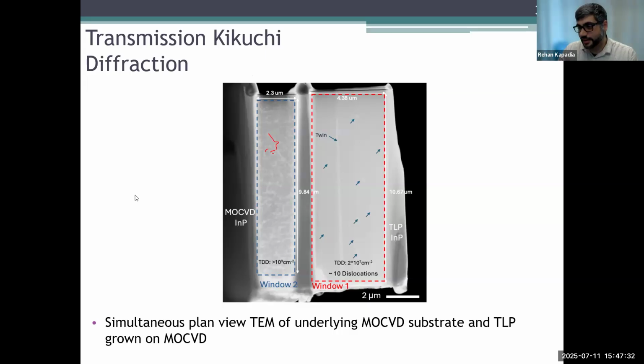And this is a very compelling proof, because essentially what we're doing is we're showing as much of the mesa as we can. So, we grew like a 10 by 10 mesa, and this is showing, or maybe I think this was maybe a 20 by 20 mesa. And then we're showing about 5 microns by 10 microns of it, which is limited just by the fact that it's extremely hard to do these kind of plan view TEM cuts and then imaging. And so it took a lot of skill and expertise. And in fact, this was something that I had sent out to a professional company to do, and they failed multiple times, and we finally just ended up sucking it up and doing it in-house. So this was something that was super interesting.